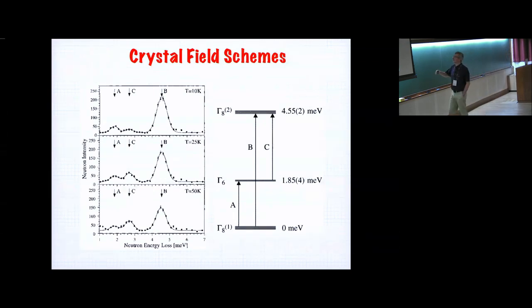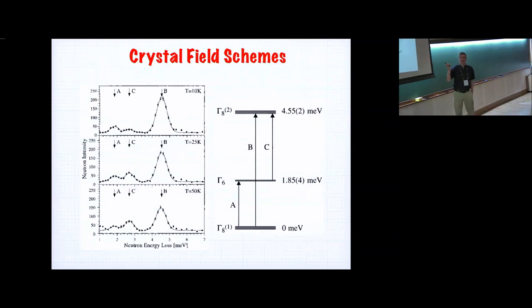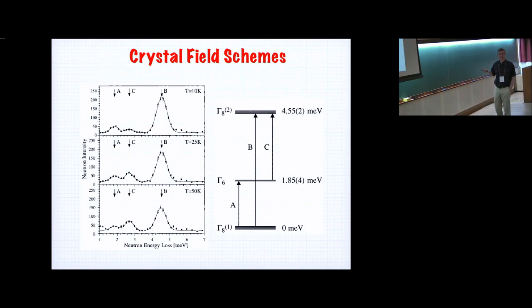Because your thermal energy, 1.8 meV, is about 30 Kelvin, so you have to go significantly below that to make the probability 0. But even at 10, it's a small peak. If you go to 5 Kelvin, this might vanish completely. And if you go up, it will maximize when this is fully populated and then start falling down again.